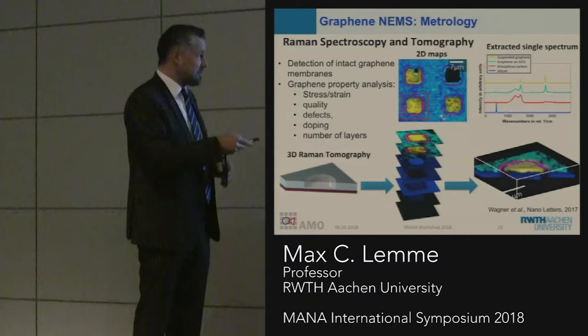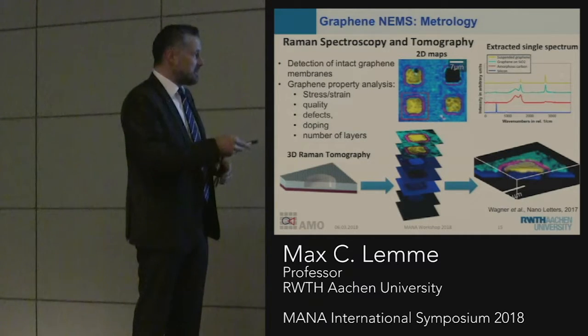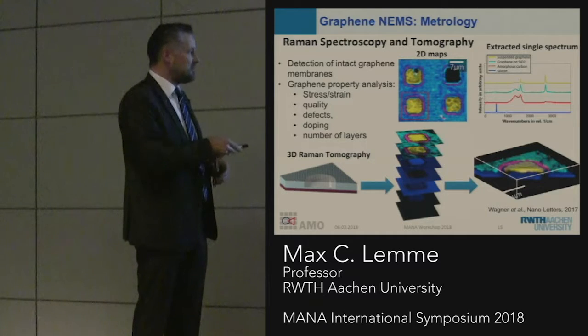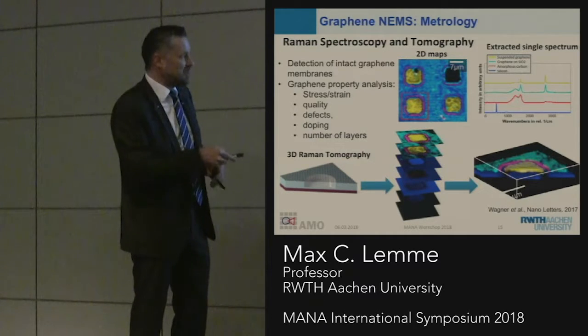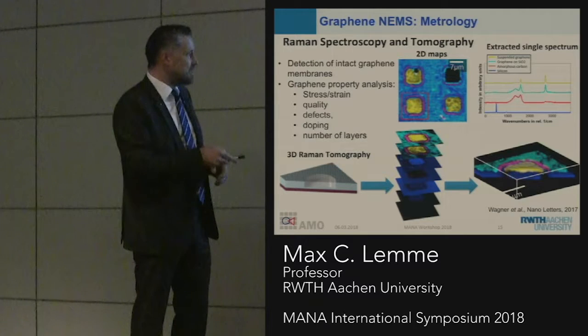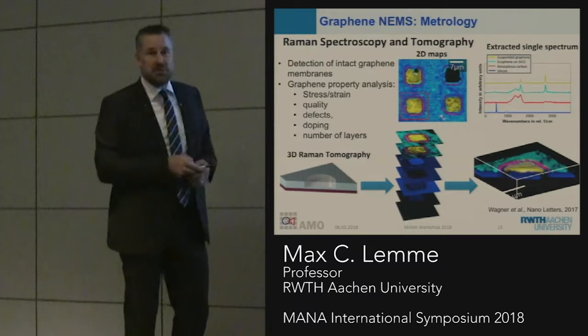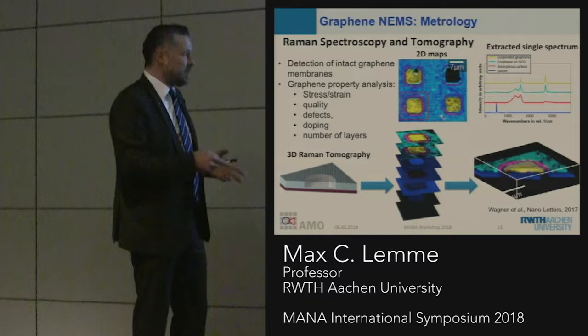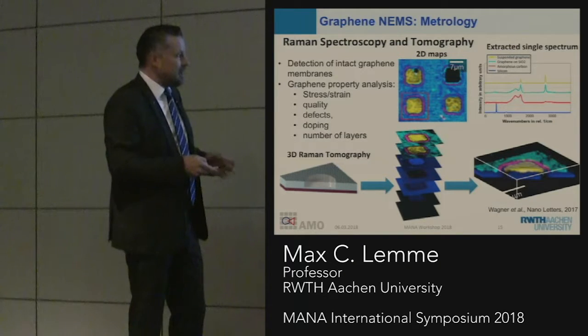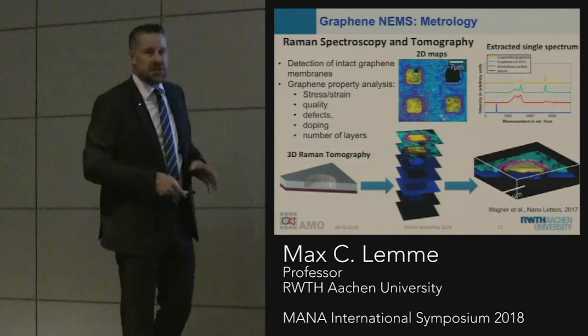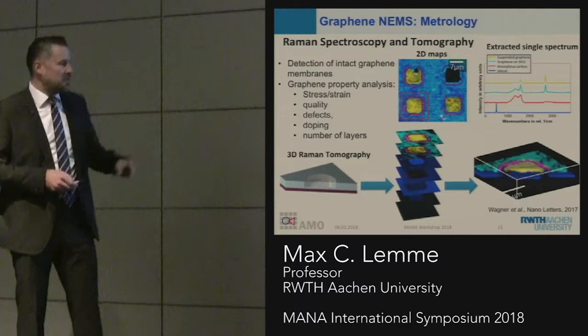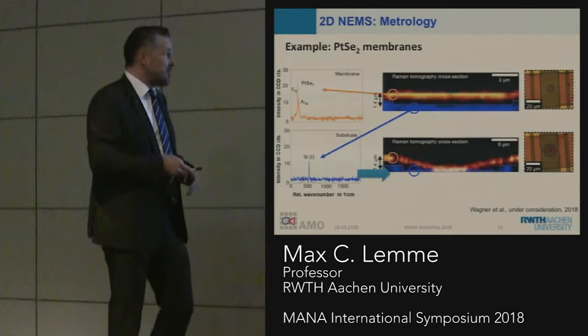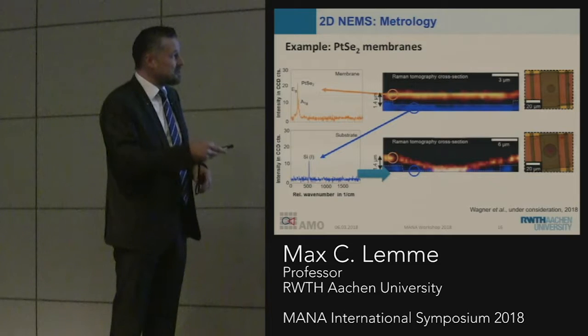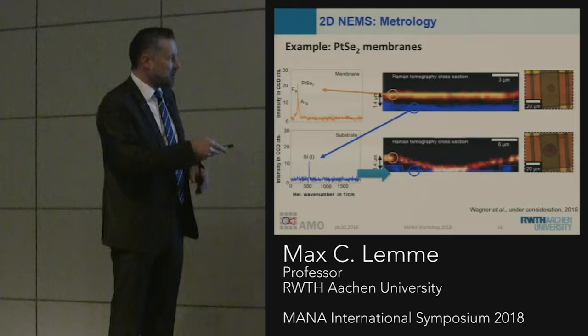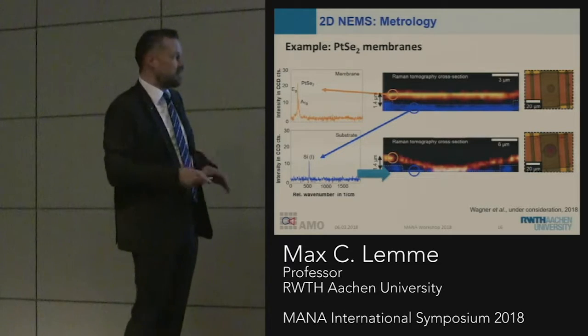We also went and did some 3D imaging, and we did depth cuts of these devices, and then we can reconstruct even a 3-dimensional form of this device. This is what we call 3D Raman tomography, and it's a nice way to investigate NEMS devices, even though the Z resolution is not very good - but for our purpose this was very nice. We also applied this to the platinum diselenide, and you can see here this membrane was intact and we were able to measure it, whereas this membrane collapsed and was attached to the bottom of the cavity.